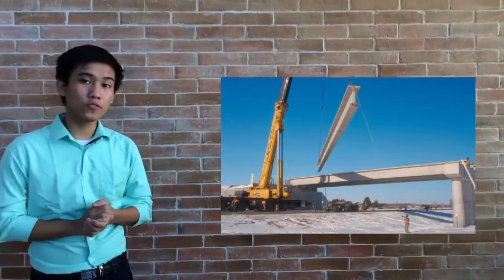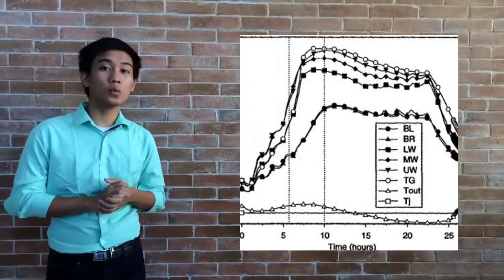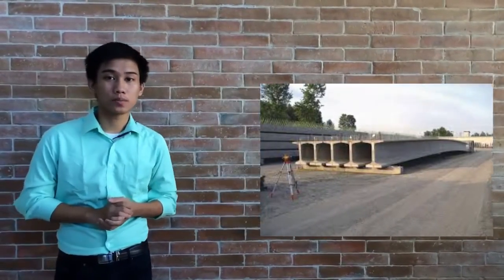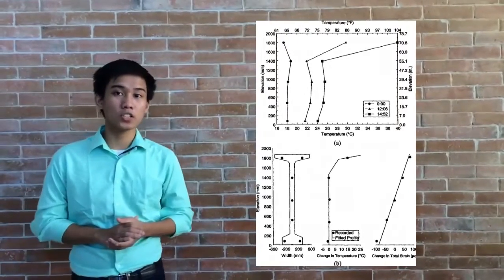The monitoring of a precast pre-stressed girder bridge during fabrication and service provided the opportunity to observe temperature variations and to evaluate the accuracy of calculated strain and cambers. The use of high curing temperatures during the fabrication affects the level of pre-stress because the strand length is fixed during the heating, the coefficient of thermal expansion of steel and the concrete differ, and the concrete temperature distribution may